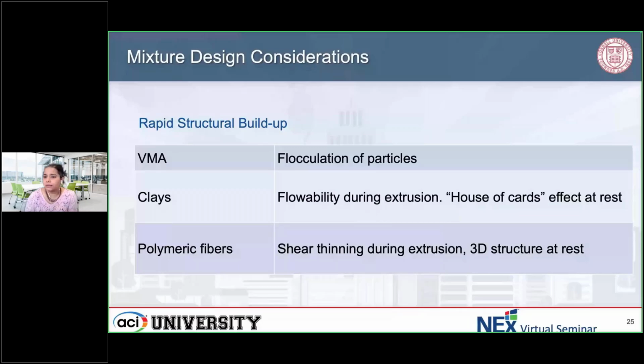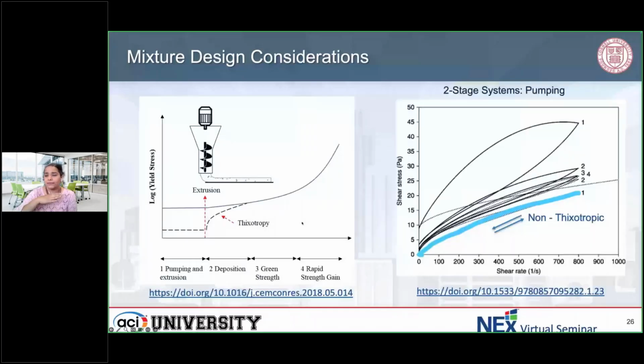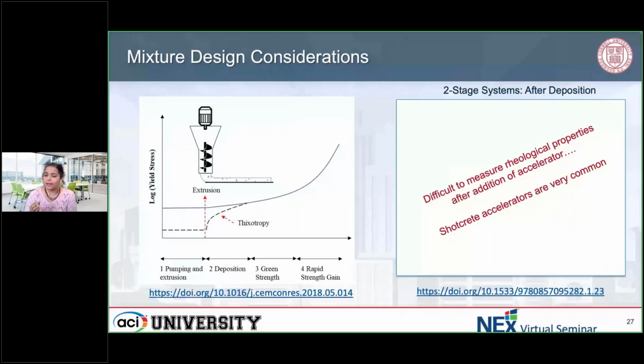But in two-stage pumping systems, because we are pumping the material, you design it such that it's typically not thixotropic, and the yield stress maintains itself over a period of time and is not changing, so that you don't have an increase in pumping pressures. It is really difficult to measure the thixotropy once you add the accelerator, because it stiffens up really fast and you won't be able to measure it using a rheometer.